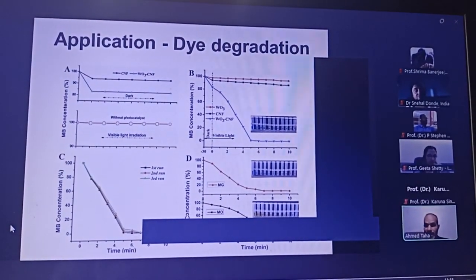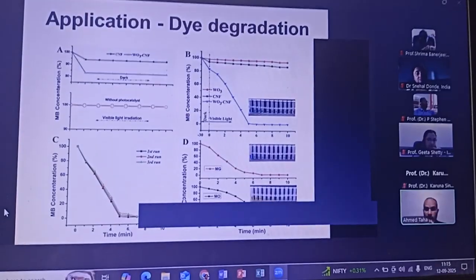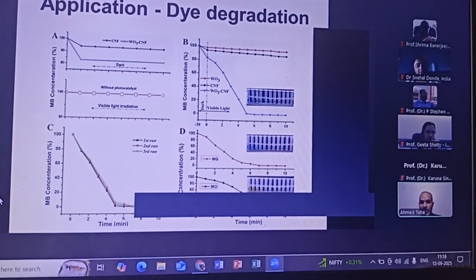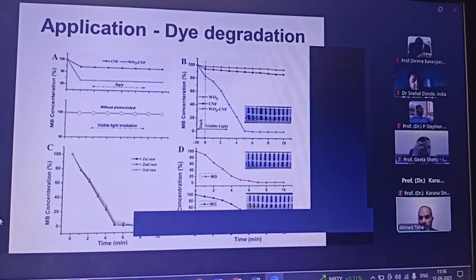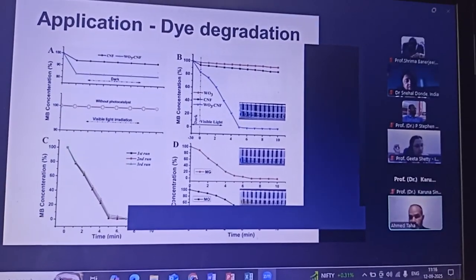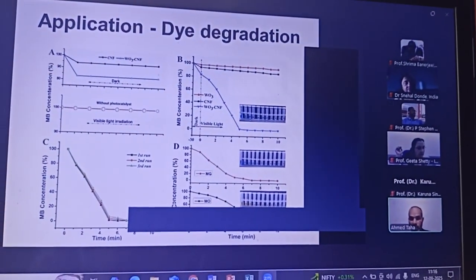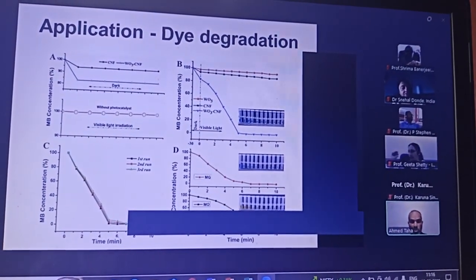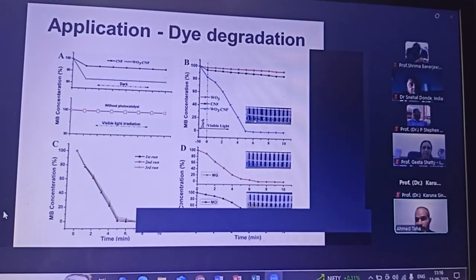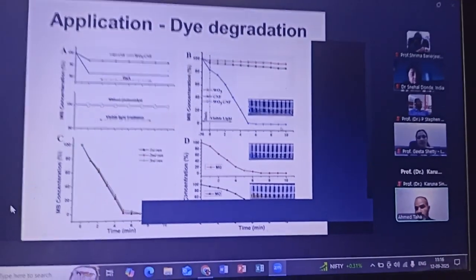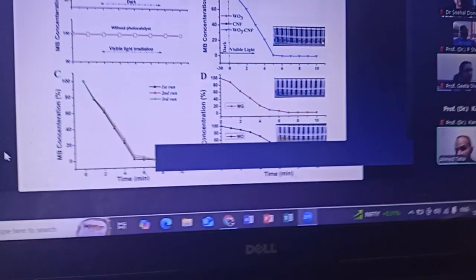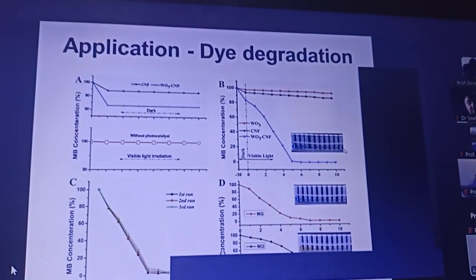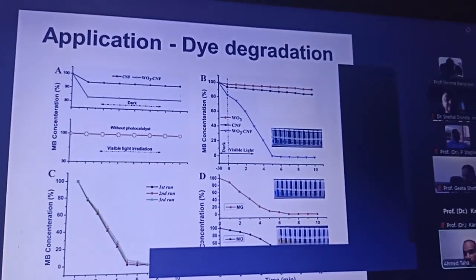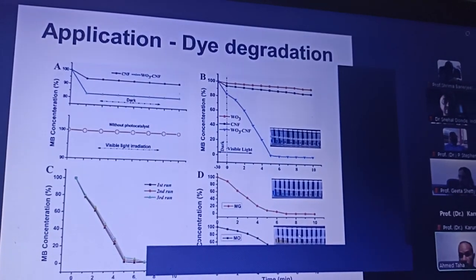So we mix the water that has the pollutant with our material, expose it to the visible light, and take samples every some minutes and measure the concentration of the dye. As you can see, the dye can be degraded, and here is a visible image. In several minutes, like in 10 minutes, we can get rid of all of the dye in the water. We have used different kinds of dyes to confirm the performance.